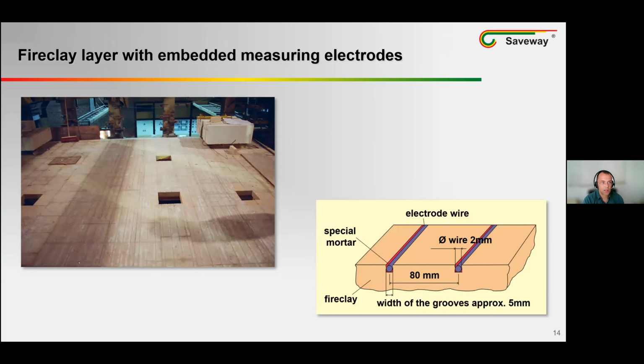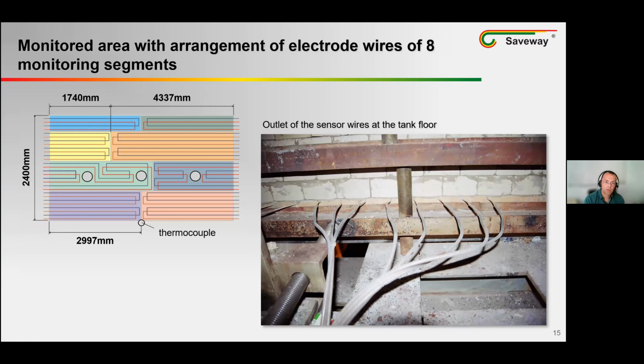The wire diameter of the electrode sensor is 2 millimeters. The groove height is about 5 millimeters. According to the above example, the area covered by 8 different colors in the picture is the monitoring distribution of 8 segments of electrode combs. In this way, the defect at a certain segment of the electrode can be located. The picture on the right shows the dedicated connections with the electrode protruding at the tank floor. The combs do not touch each other. In reality, the wires are laid 40 millimeters apart in height at the intersecting lines in the sketch.